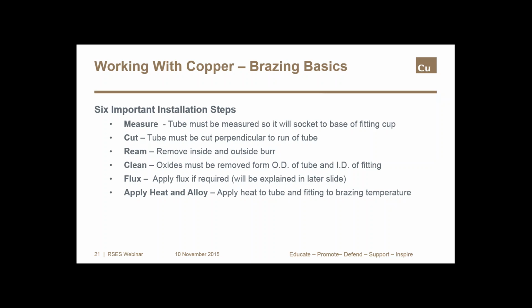Dirt, oil, and oxides that form on the surface of all metals will interfere with the flow of molten braze alloy. And this flow of alloy is absolutely essential to the quality of the finished braze joint. Oxides must be removed from the outside of the tube and the inside of the fitting. If flux is required, it's applied to the clean tube and fittings before the assembly is heated to braze temperature.